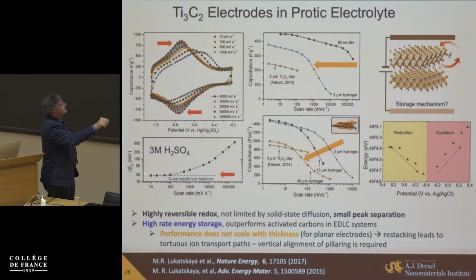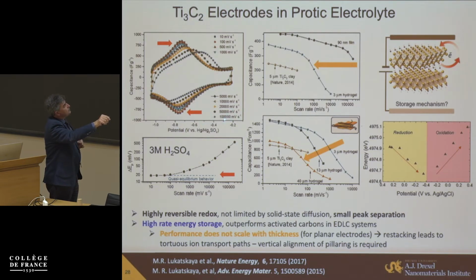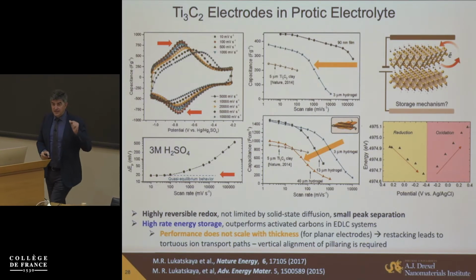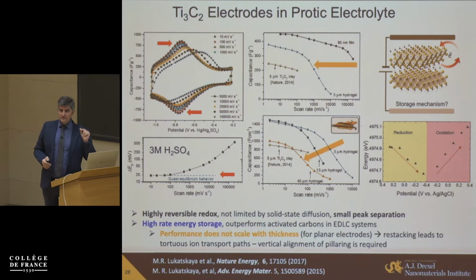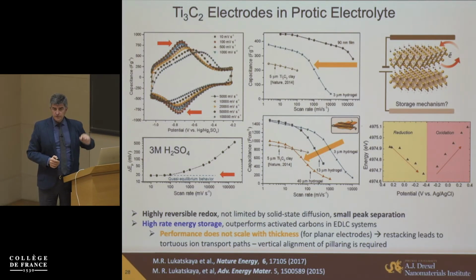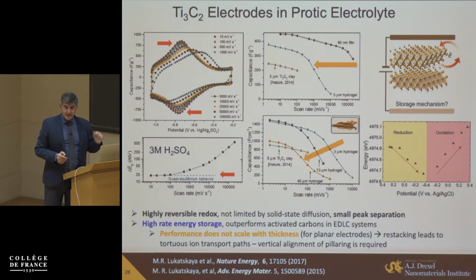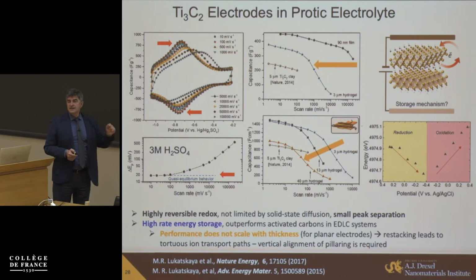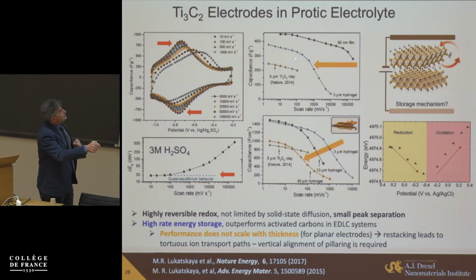The separation is 20 millivolts between the couple of the redox peaks here. But what is interesting, you go to 100 volts per second, enormous rate, 10 millisecond, 1 volt charge discharge, and you still have this peak. So you still have a redox storage at these rates here. So what does it mean? If you have high electronic conductivity and ability to deliver fast diffusing ions, protons, you can get redox storage at virtually any rate. The question is to be able to overcome this limitation. And not electronic in this case. This was for a 90 nanometer thin electrode.